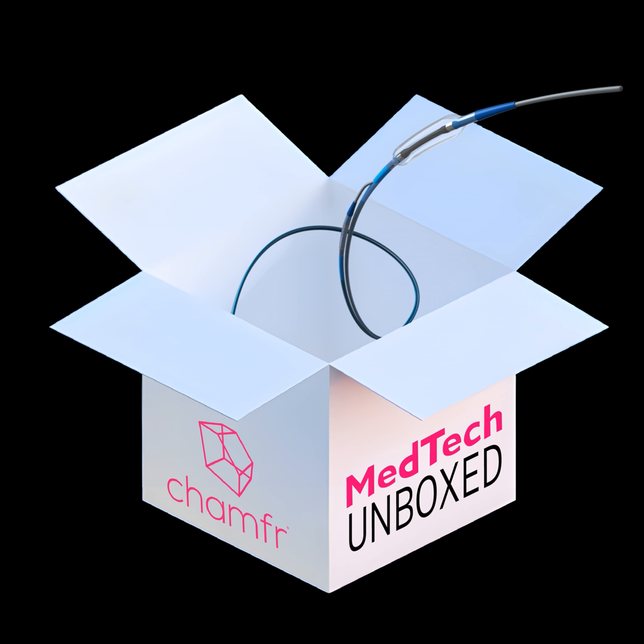Particularly, we're working on really small parts with really, really tight tolerances. So thin wall conditions, small gates, places where a little bit of shrinkage variation can have an outsized impact on the tolerancing. So we have to put a lot of work into doing mold flow analyses and simulations to predict some of that, decide if we need to add extra gates or move gates or thicken wall sections or redo geometry so that we're controlling where a knit line is going to land, things like that.